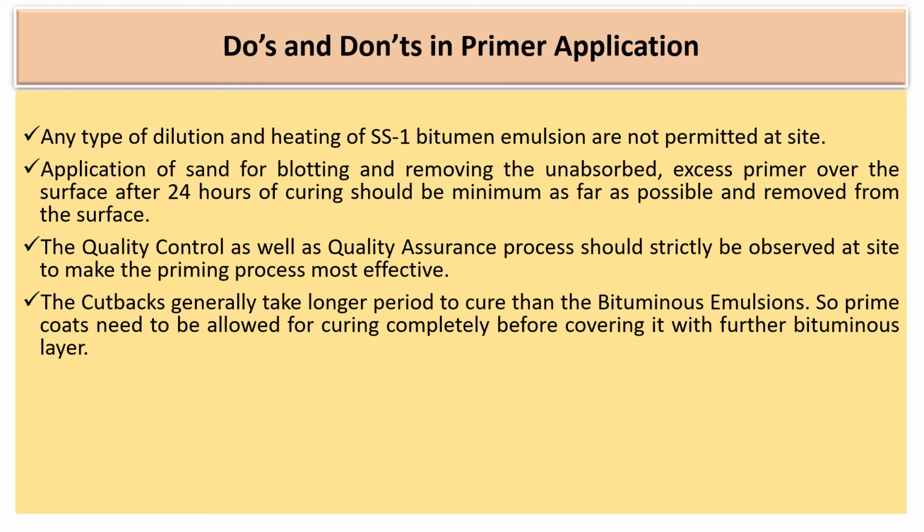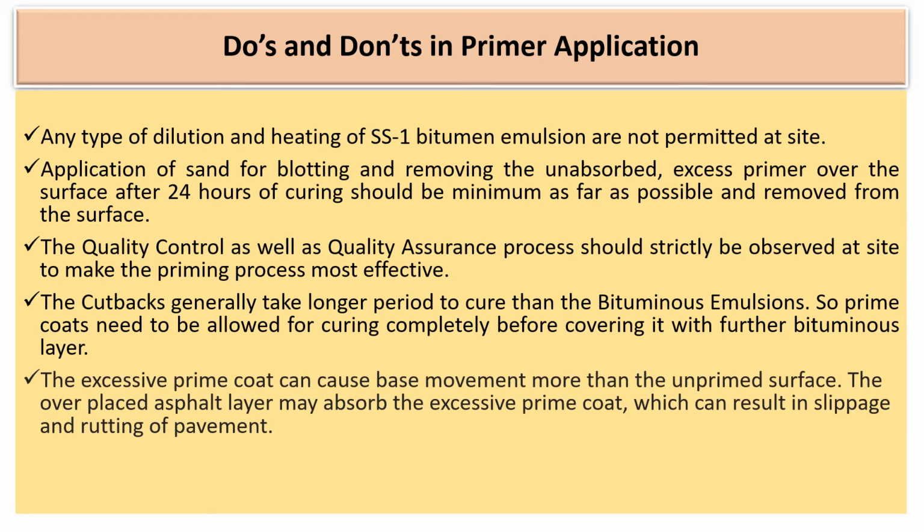Different types of liquid bitumen have different curing periods. So, special attention should be given for complete curing of prime coat before laying any further course of bitumen layer. Excessive application of prime coat is not advisable as it may be a cause of base movement. The superimposed asphalt layer may absorb the excess prime coat to its level. As a result, the bituminous pavement will show slippage and rutting types of defects in its surface in the latter period.